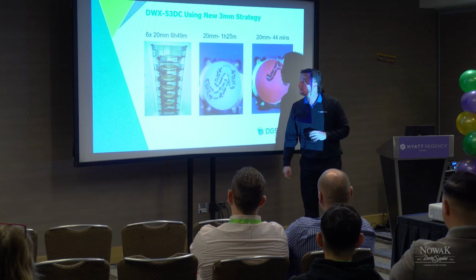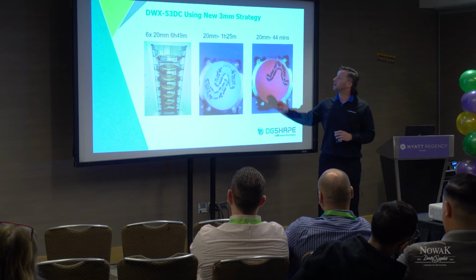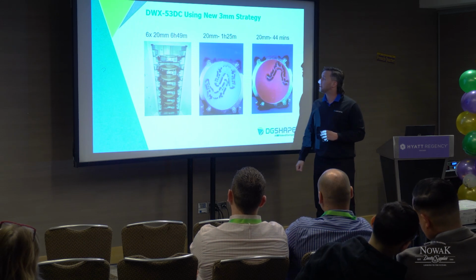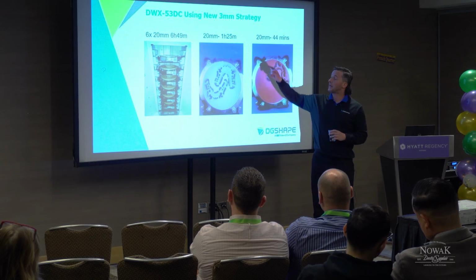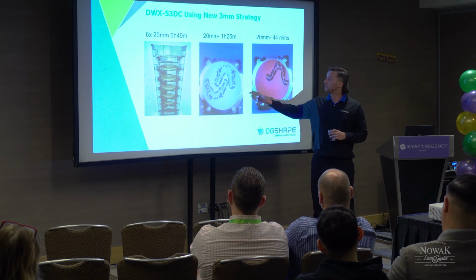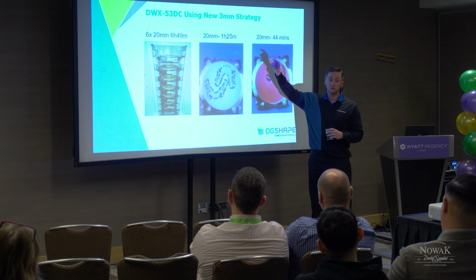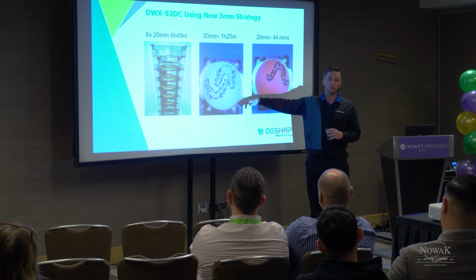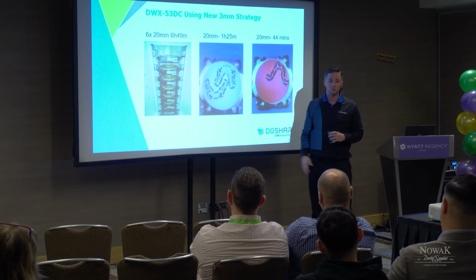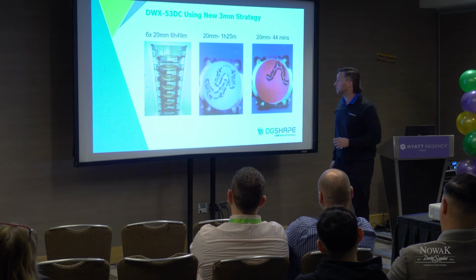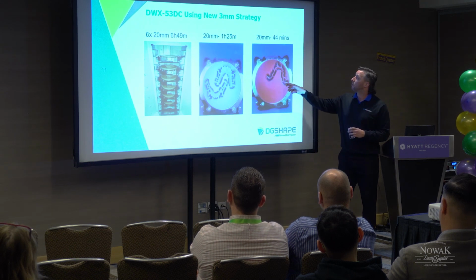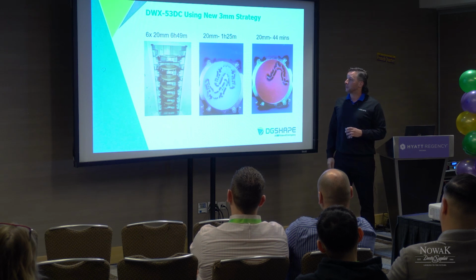VisiClear RPDs, if this is a workflow that you're doing, we are able to mill 2 flexible RPD frames in just 1 hour and 25 minutes. In that previous slide, a job like this was twice as long. We took off 1 hour of milling time, which is significant with this new strategy in the RSB 150D tool. And then we have a 4 millimeter RPD frame here as well.